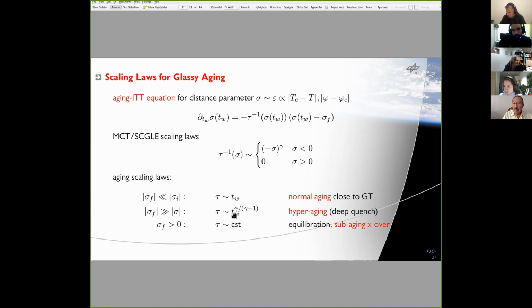And if you work out the MCT exponents gamma, you discover that this exponent here that we get for quenches deep into the glass is always larger than 1. So you can call this hyperaging or whatever. And again, that's a term that has been used variously. And this is then what the theory predicts.